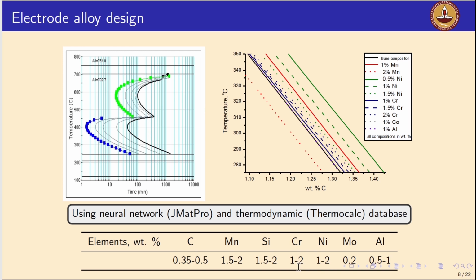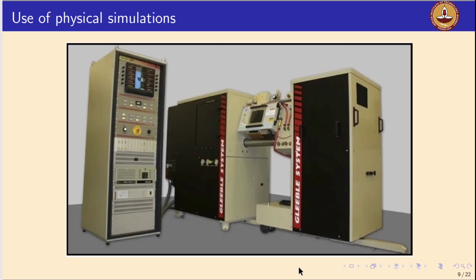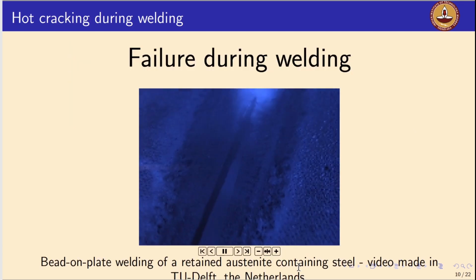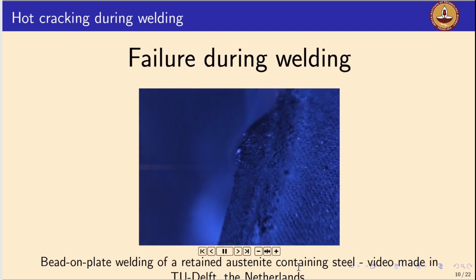So once we make these electrodes and we start producing the candidate welds to generate samples for the physical simulations, because immediately when we start depositing the welds, the welding thermal cycles are not optimized, right? So we generate the candidate welds, and subsequently we extract the samples from the candidate welds and carry out extensive physical simulation using Gleeble. Right. So the first simulation we carry out from the candidate chemistries is to understand the hot cracking susceptibility.